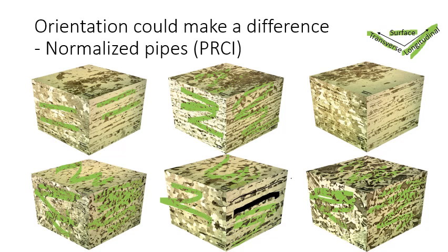But it's really interesting here on the surface because of the different cuts. What's going on here is you see these splotches of dark phase, a lot more dark phase, and then a region with a lot less dark phase. That's because of the angle at which we're intersecting those bands with the surface analysis.